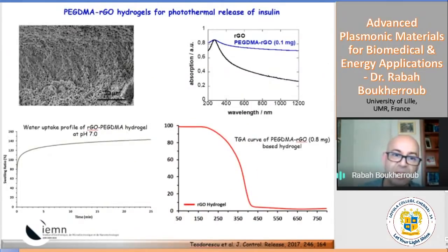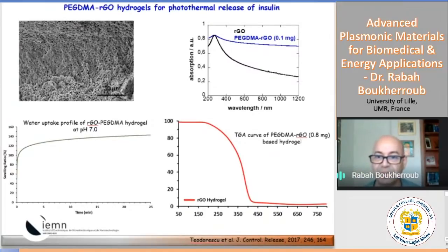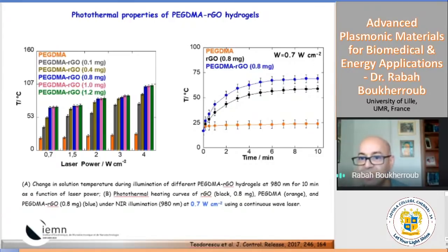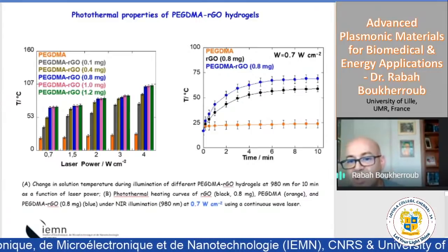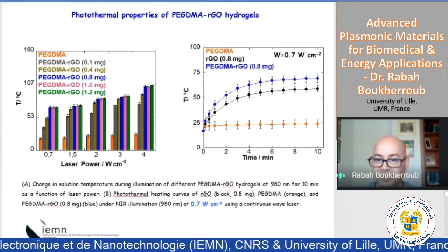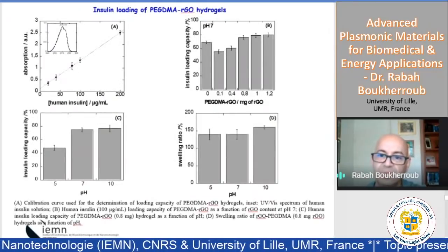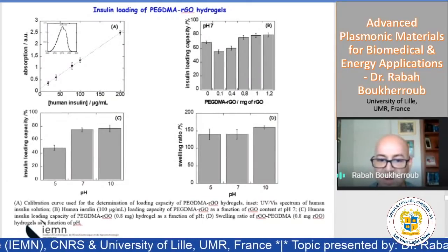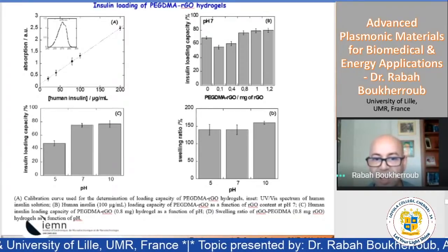Interesting enough, it's a porous material. If it's porous, it's a hydrogel, so it can really load a huge amount. It can also protect the drug because it's an environment with a lot of water, and it's thermally stable, because I have to actually generate heat. And importantly, if I expose that to light irradiation at 0.7 watts per square centimeter with just a laser at 980, you can heat up over 60 degrees. Of course I don't need this high a temperature, just about 50 should be more than enough. All said, we optimized the ratio between the polymer and the reduced graphene oxide, and the pH at which you load. I will go fast now anyway.